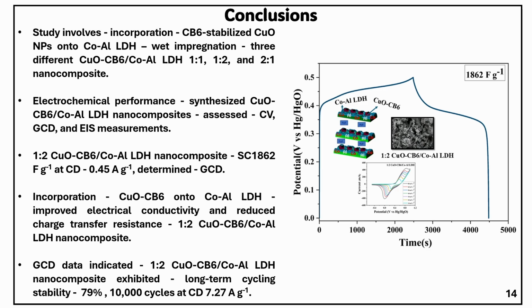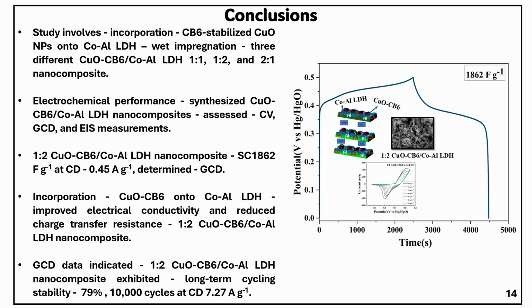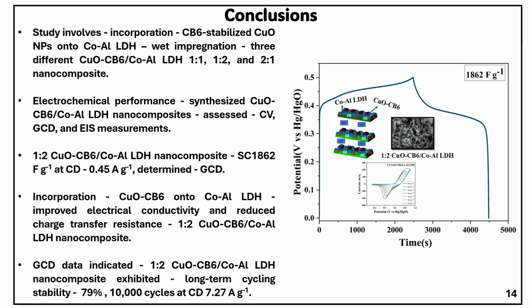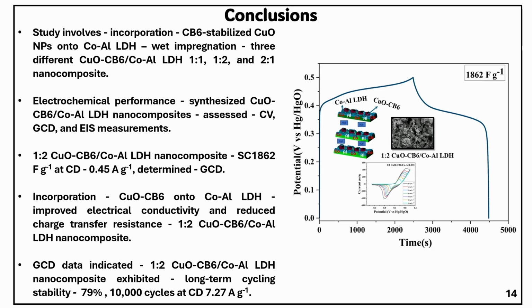Next, I would like to conclude this talk. This study involves the incorporation of CB6-stabilized CuO nanoparticles onto the cobalt aluminum LDH layers through the wet impregnation method to produce three different nanocomposites: 1:1, 1:2 and 2:1. The electrochemical performance of the synthesized nanocomposites was analyzed through cyclic voltammetry, galvanostatic charge-discharge, and electrochemical impedance spectroscopic analysis. The 1:2 nanocomposite exhibited a specific capacitance of 1862 farad per gram at a current density of 0.45 ampere per gram as determined by GCD analysis.